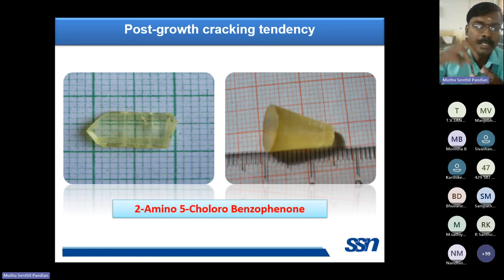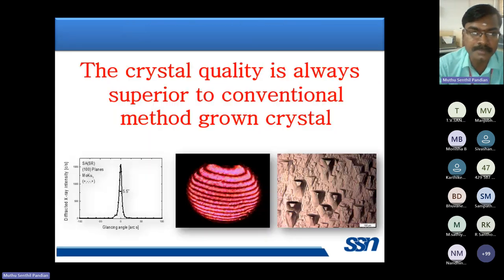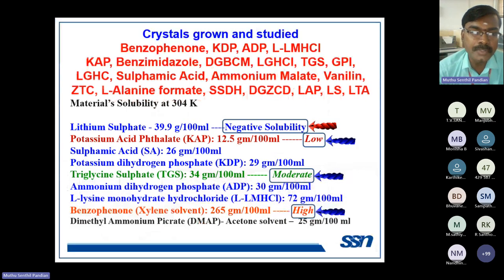top and bottom portions. So with uniform solvent evaporation and stable supersaturation, there is no possibility of the formation of multinucleation, milky opaques and microcracks in the SR method grown crystal. So the crystal quality is always superior to the conventional method grown crystal. This we have confirmed with several characterizations like HR XRD, birefringence, chemical etching, optical transmittance, UV-Vis-NIR, Vickers microhardness and so on. As I mentioned, so far by this method, more than 200 crystals have been